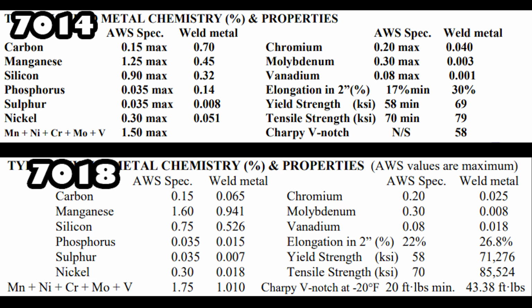Tensile strength 70,000 minimum. 7014 actually tests at 79,000, and if you look at 7018, it tests at 85,000, so massively higher than 7014. And I think that's part of the reason why we're going to see that 7018 passes in this test and 7014 doesn't.